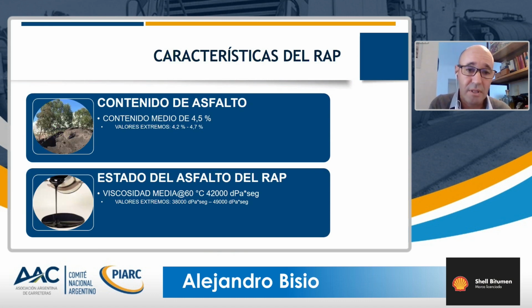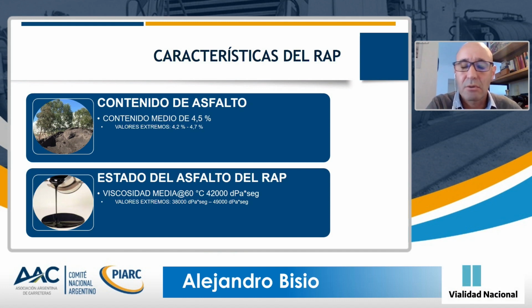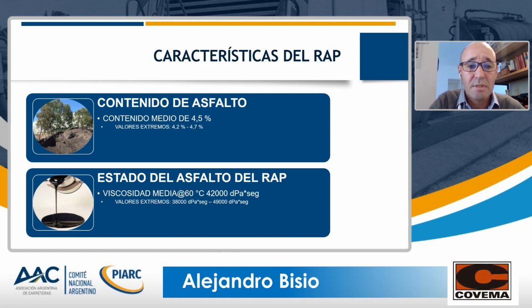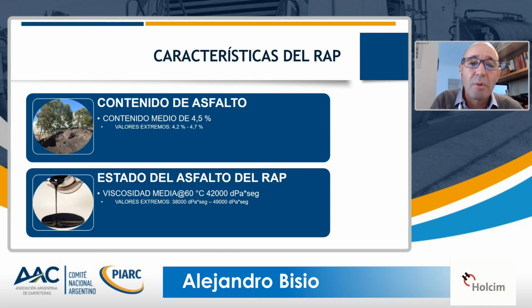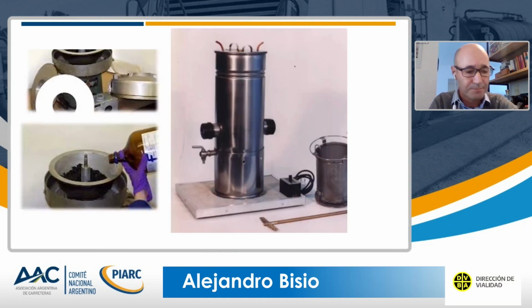As to the RAP features, the mean optimal asphalt content throughout the works was approximately 4.5%, and the status of the RAP asphalt as regards its behavior had 60 degrees viscosity, and so the mean value, considering natural fluctuations because it's a recycled material, was 42,000 decipascals per second.